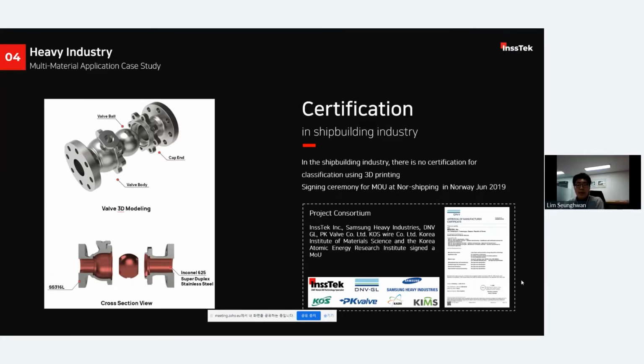And the valve can be separated into 2 regions. As you can see in the graphic in the bottom left, there are 2 color regions, red and gray. The red region is vulnerable to corrosion due to direct contact with seawater. So we made the red region with Inconel alloy, which has high corrosion resistance. The outer gray region is made with stainless steel, which is easy to machine.